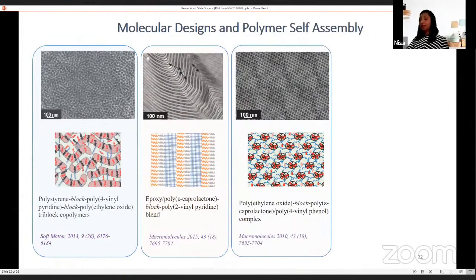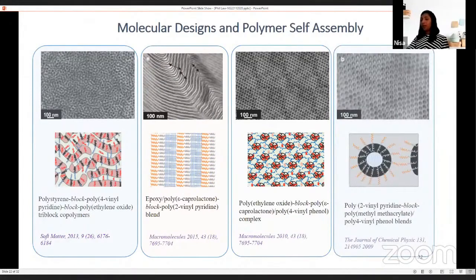Here you can see some hexagonal arrays of nanostructures with size around 30 nanometers. Here we used a double crystalline block polymer blended with a homopolymer system. The last one is showing hexagonal cylindrical arrays of polymer chains. In summary, we have created various nanostructures both in solution and solid state. We can control the morphologies, or switch the morphologies, by changing their molecular weight or chain length, or even the composition of each block in the block polymer. We have also derived a mechanism for these materials to understand the structure formation.